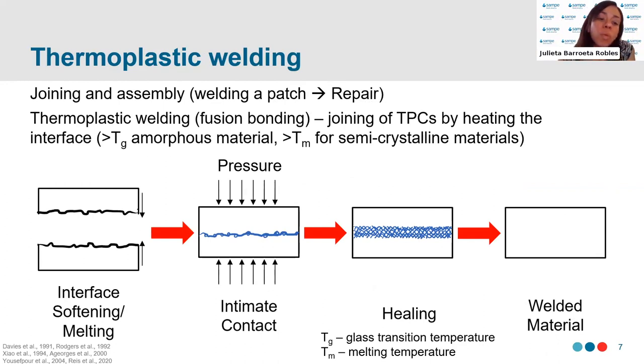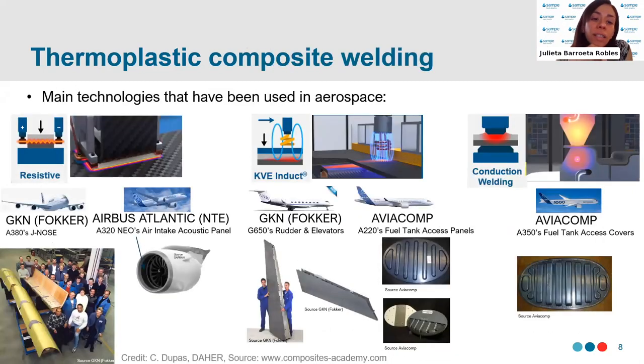In thermoplastic welding, we will increase the temperature at the interface in order to soften or melt the material, if it's an amorphous or a semicrystalline material respectively. Then we're going to bring the adherents into intimate contact by applying pressure, at which point interdiffusion of the polymer chains is going to begin in a step called healing. And then once the interface has fully disappeared, then we have attained a fully welded material. The interlaminar bond strength is a function of the three most important parameters in thermoplastic welding, which we know is temperature, pressure, and time.